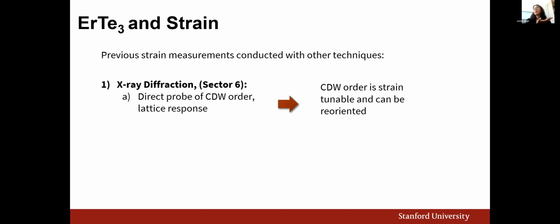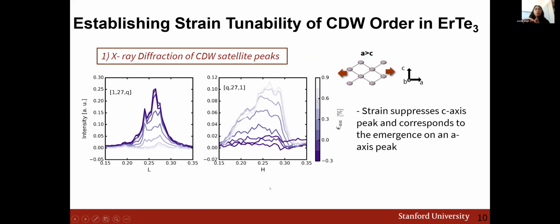And I want to share a little bit about these other things that we've observed in this material through the application of uniaxial strain, starting with some X-ray diffraction measurements that were also done here at the APS at Sector 6. X-ray diffraction is a very powerful tool to study this material because it provides a direct probe of the charge density wave order by observing the superlattice peaks and how they evolve with strain. And what these measurements show is that the CDW order indeed responds to strain and the primary CDW wave vector can be reoriented.